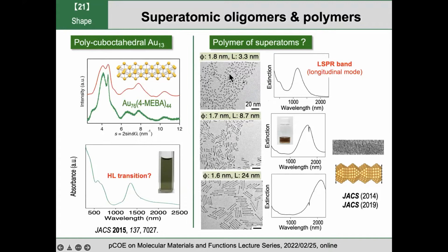And here's another example. As you can see by TEM, this is not atomically precise, but the diameter is always smaller than 2 nanometers, and we can change the length of the structures like this. And this looks like a very tiny rod, okay? And these clusters exhibit localized surface plasmon along the longitudinal mode, okay? And this mode is redshifted with increase in the aspect ratio. And this one is a very intense band.